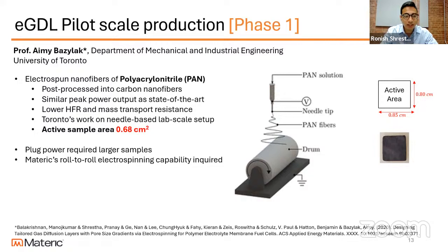They were able to see comparable output and performance to the state-of-the-art GDLs. They were also able to see lower HFR and mass transport resistance values that were very promising results. But all of Toronto's work was on a needle-based system. The active sample area that they were working with was less than a square centimeter, and Plug Power, which is